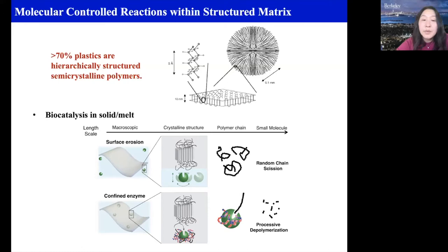But on the other hand, if you confine your enzyme, in particular if you can do a nanoscopic dispersion of your enzyme, you really open up a lot of opportunities. For example, the enzyme will only go into the amorphous domain. So this is what you have here. In the amorphous domain, polymer chains are not crystalline. So they often have mobility and they are randomly arranged just like spaghetti noodles in a bowl.